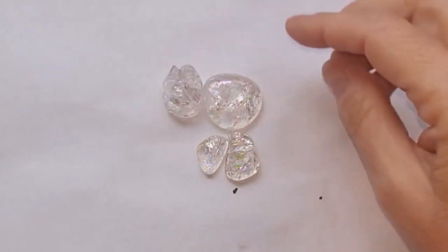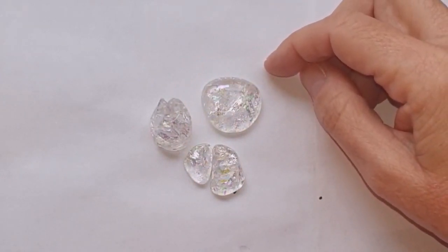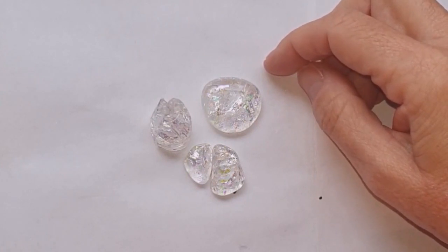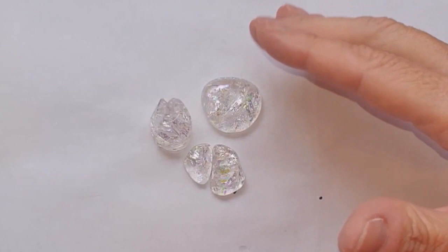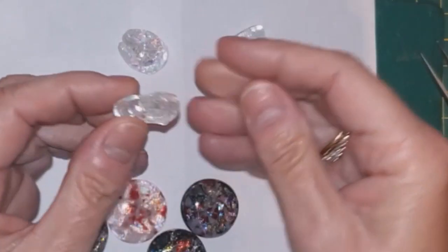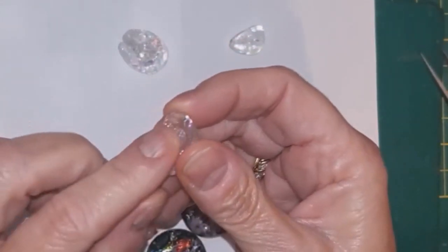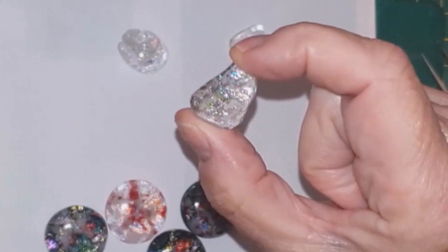To mention as well — the fact that this broke — I just went up to 100% full power. I did half expect it would break anyway, but that's how you sometimes come up with nice pieces when things get out of control. If I'd done it slowly — at 50, 30, or 20 percent for a few minutes and then gradually worked up to 30, 40, 50 percent power — it would have shocked the glass less and probably not broken. But I'm a little bit impatient like that, as I'm sure a lot of people are, and I knew it wasn't going to be disastrous. This last little one I'm actually going to put on the grinder on the back to create a frosted effect — that should make it look more like an opal.